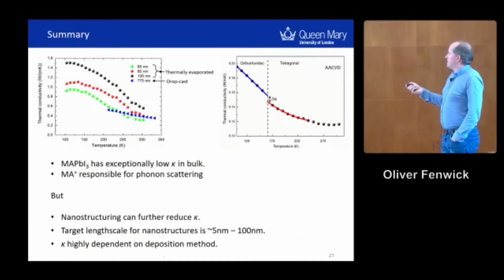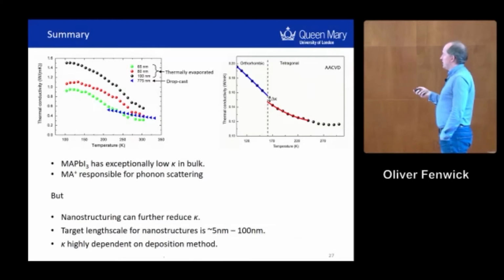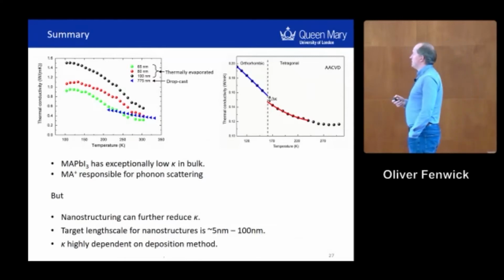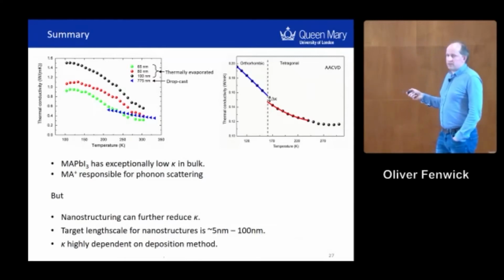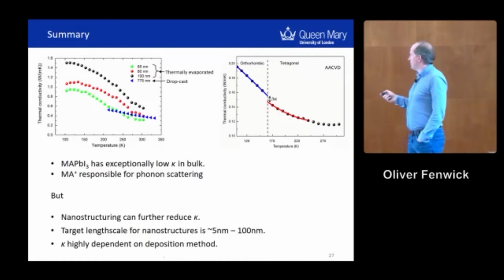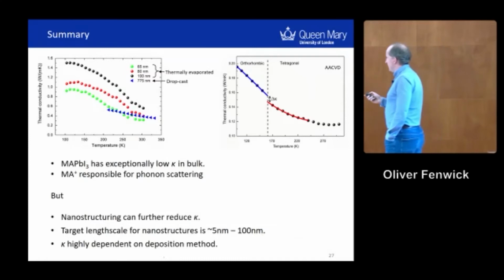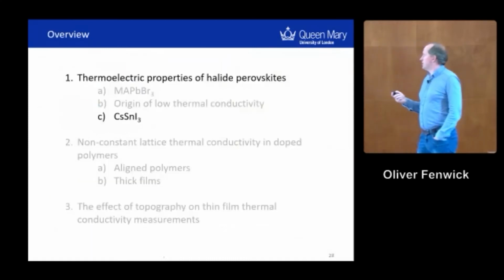But I think the key messages are, yes, these halide perovskites have exceptionally low thermal conductivity in bulk, but we can use nanostructuring to reduce that even further. If we use nanostructuring on the scale of about 5 to 100 nanometers, the thermal conductivity is highly dependent on the deposition method.